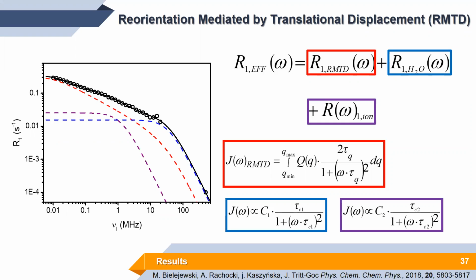Okay, but still we have hope, as hope dies last, that maybe in the ionogel the situation is a bit different. So we use the RMTD model to analyze the NMRD profiles for the ionogels. And this is an example of a 500 millimolar ionogel. So we add another contribution just to describe the molecules which actually create the solvation shell around the ions. So we have a contribution for the solvation shell. We have the contribution for the molecules which are close to the surface of the gel matrix but do not interact directly with the surface. And we have a contribution with the molecules which directly interact with the surface of the gel matrix.